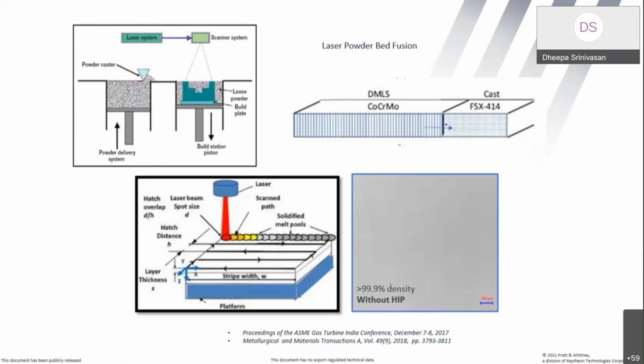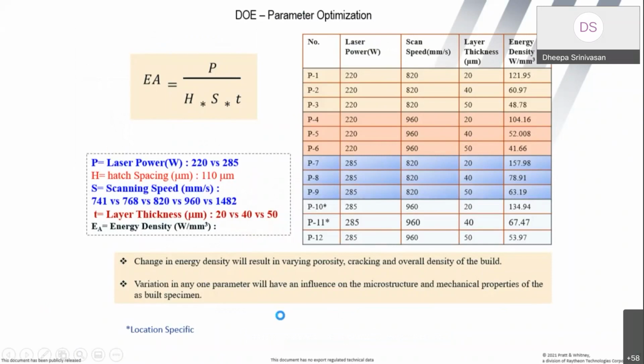So what is the starting step out here? The starting step is to actually map the process parameters to give a part with 99.9% density. So that is what this is, cobalt chrome moly, this one, and this is being attached to an investment cast FSX 414. I showed you a couple of slides ago the kind of complexity you have in the powder bed fusion technology. So what we did is we optimized, this was a master's thesis of a student from PSG Tech. We optimized very quickly in February and March of 2015 a design of experiments based on laser power, scan speed, and layer thickness in the powder bed fusion process in order to actually get a dense part.